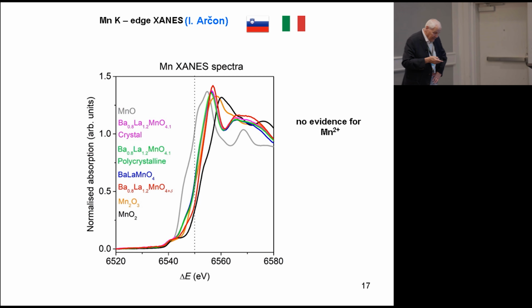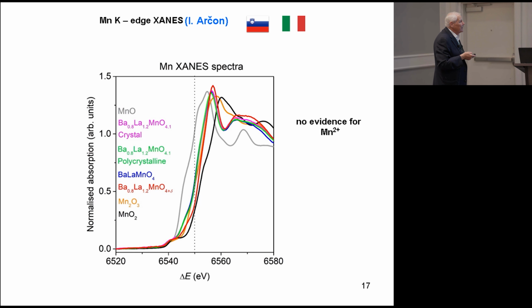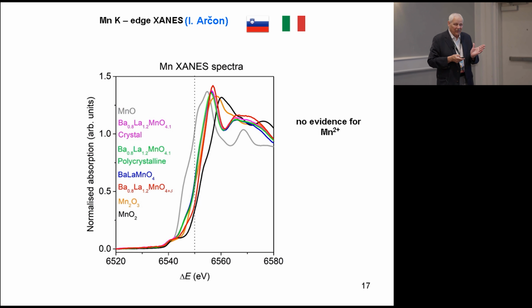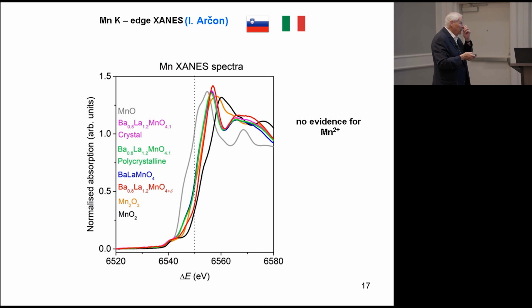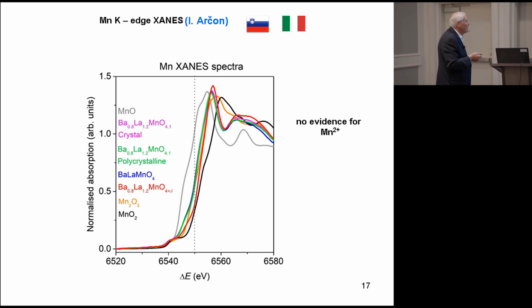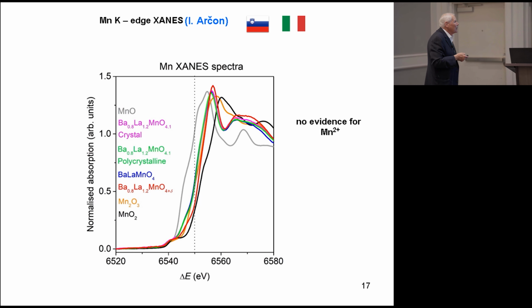Okay, so here we have to use other techniques. We have a collaborator, and we took some manganese K-edge XANES spectra, and this is our sample here in red. This is what you would get if you had any manganese 2+. So there's no evidence for manganese 2+. We have to have all manganese 3+, which leaves us with the problem: where's the bloody oxygen?